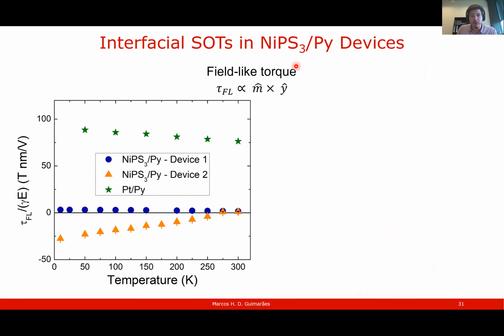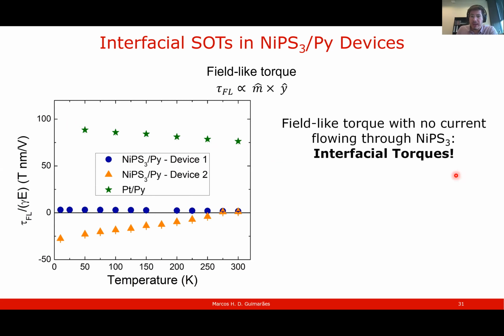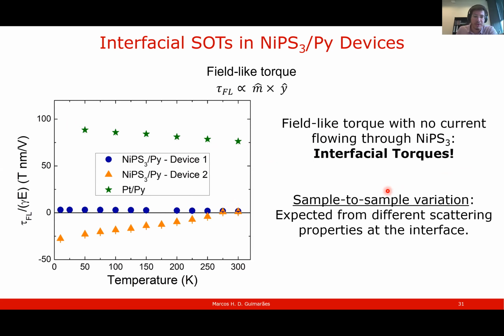So if you look at the field-like torque, now this is the torque that looks like an Oersted field, but you have to remember there is no current going through the nickel thiophosphate because it's so resistive. And the torque intensity as a function of temperature here, it looks like there is a temperature dependence. And it varies from device to device. It can even change sign. And well, it's below the platinum. So here you can see in the green stars, you have platinum permalloy. It's much below that just because, well, we have no current going through. And this gives you a direct indication that these torques are interfacial. And the sample-to-sample variation here can be expected because of the different scattering properties of the interface between different devices.